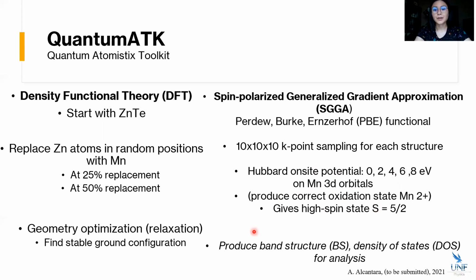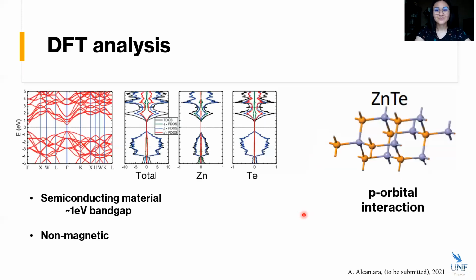We also produce band structures and the density of states to see how the electrons prefer to interact. And so this is the band structure and the density of states for the zinc telluride as the parent compound. Because the band gap is around 1 eV, this means that it is a semiconductor, which is what we want. And then if we look at the total density of states, you can see that because of the equality of spin up and spin down, it is non-magnetic, which is also what we want.